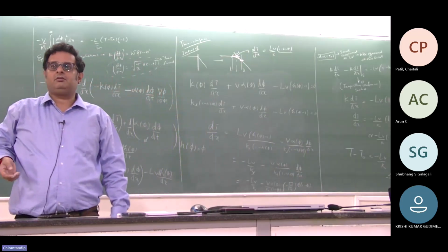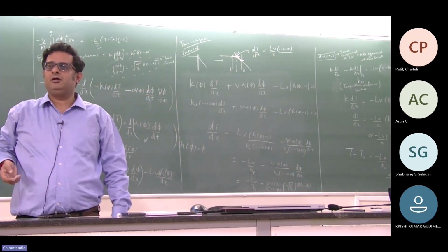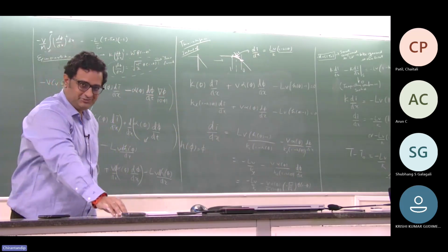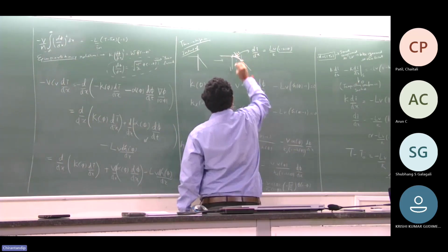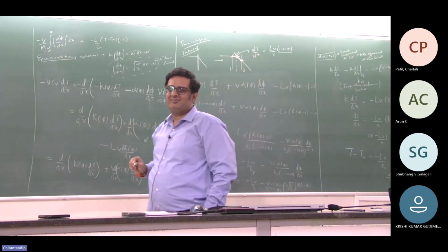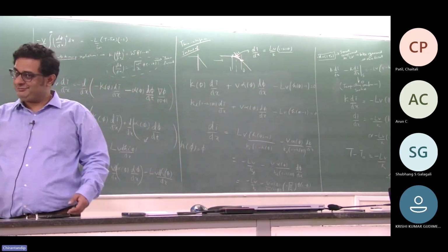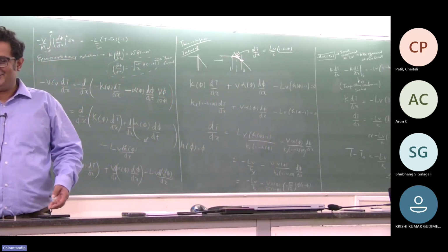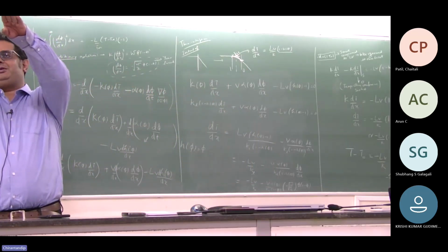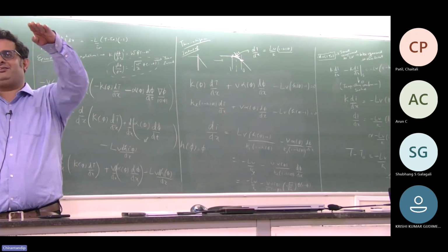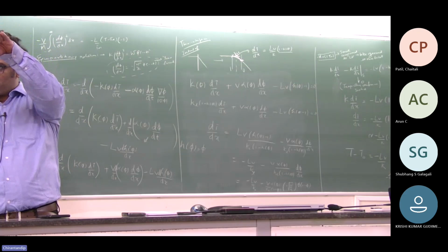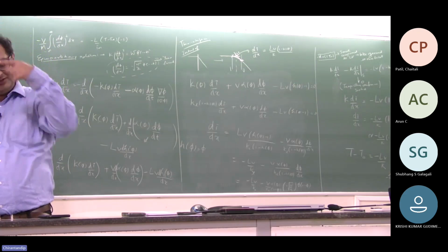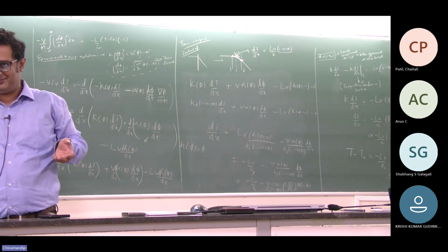Asymptotic value T star is equal to T naught. Yes, but in actually the temperature profile. Good question. So, for this to happen, the interface temperature is necessarily lower. That is because dT/dx is positive. The temperature has to be this. If your asymptotes have to meet at the correct value, the interface has to go to a lower value. Mathematically, otherwise it can't happen.